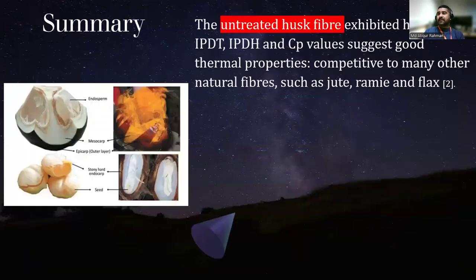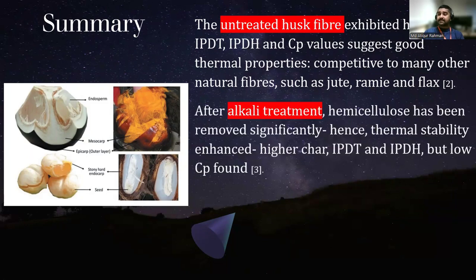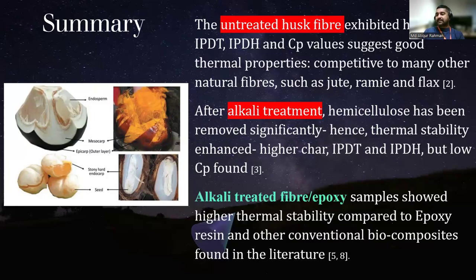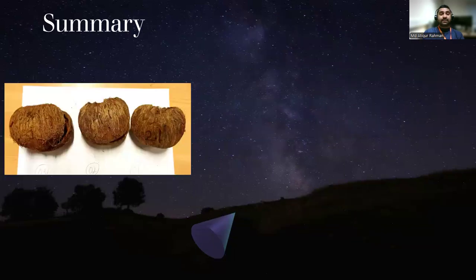So in summary, we found that the untreated husk fiber exhibited high char value, IPDT, IPDH value, and heat capacity value, which suggests that it would be good to compete with natural fibers currently being used, such as jute, ramie, and flax. After the alkali treatment, hemicellulose has been taken away significantly, because we have seen it through quite a few tests, and hence the thermal stability enhanced. We got the higher char, the higher IPDT value and IPDH value as well, although we found a low Cp value, or specific heat capacity value. Alkali treated epoxy samples showed higher thermal stability, obviously, compared to the base epoxy resin and other conventional biocomposites found in the literature or currently being used.